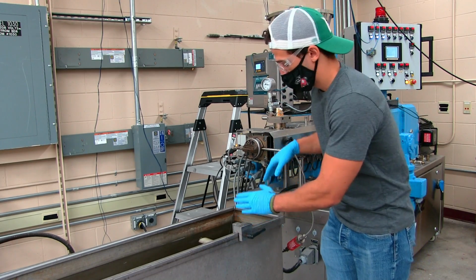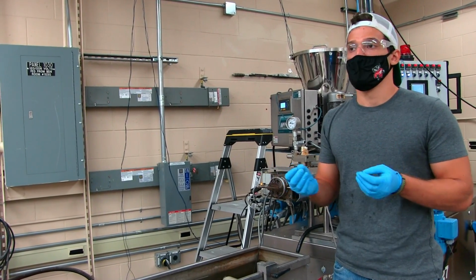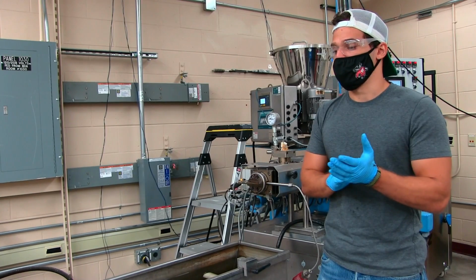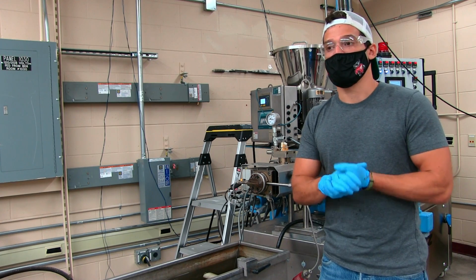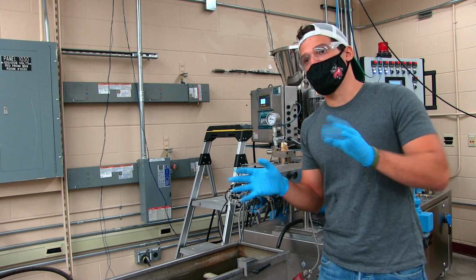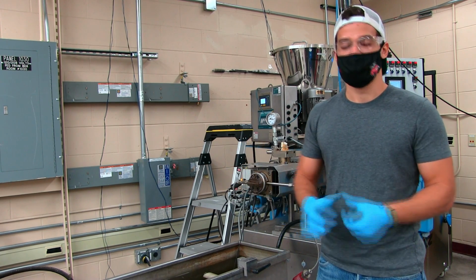So what we do is we submerge it into a water bath where it's cooled, and then it's transported to a machine that essentially consists of a rotating blade, and that allows us to chop the material into pellets again, because the 3D printer that we have here at the PEC is unlike the 3D printers you might have seen at your school. It doesn't work with filament, it works with pellets. And this has the advantage that if the material is too viscous or too brittle, you can't produce it as a filament, but you can process it as a pellet. So keep this in mind when we show you our special 3D printer in a couple of minutes, and you'll see why it's necessary to process it this way.